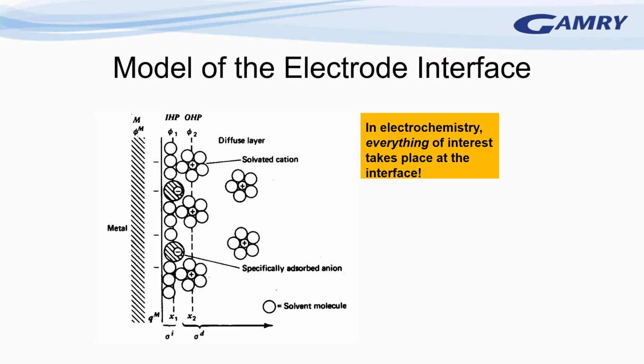And here we have a stylized model of the electrode-electrolyte interface, indicating the layers close to the electrode surface. The closest layer is called the inner Helmholtz plane, where solvent and any adsorbed ions reside, and slightly further out is the outer Helmholtz plane, where solvated ions in solution are. You can see that the surface of the electrode attracts ions from solution of the opposite charge. So in electrochemistry, everything of interest takes place at the interface.